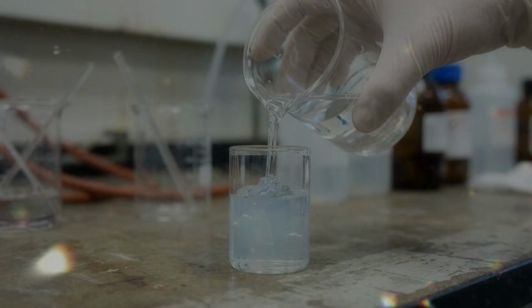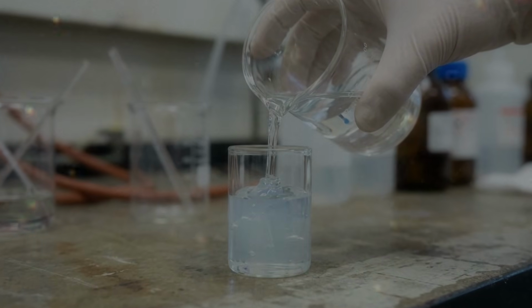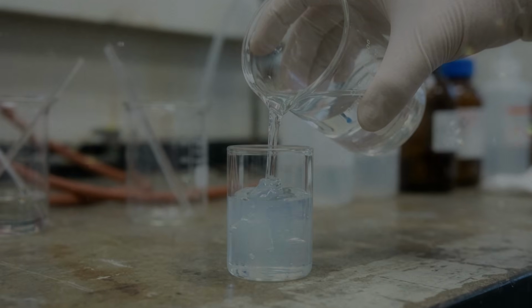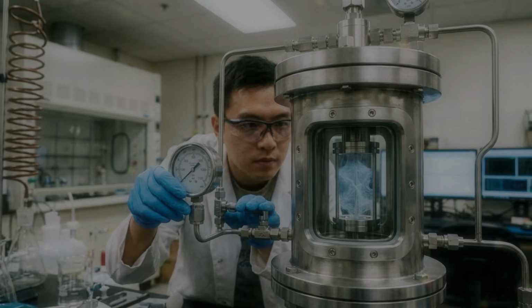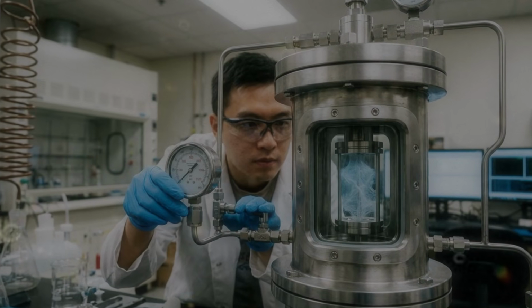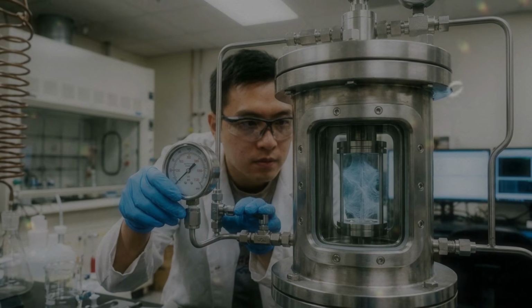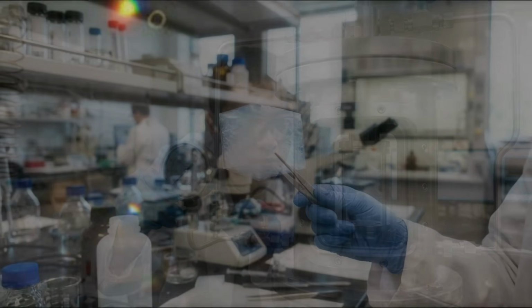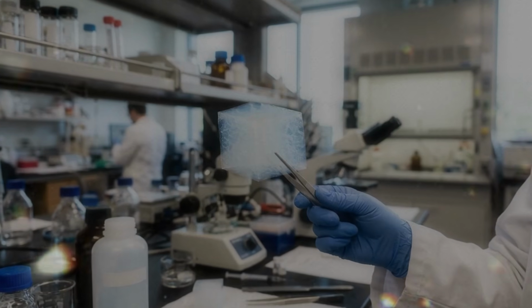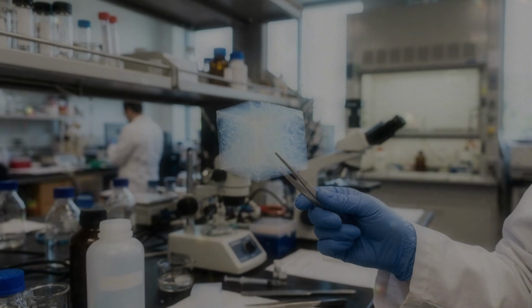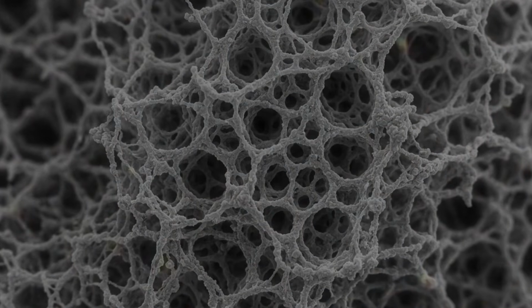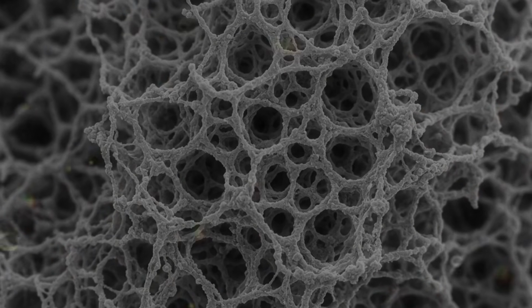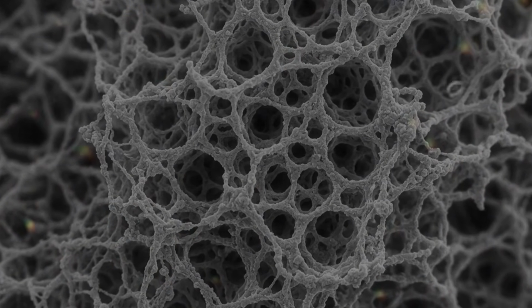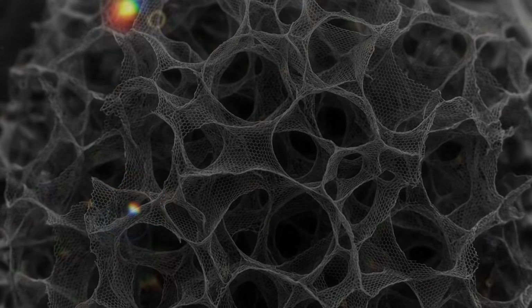A very light electrode may occupy too much volume. Thick electrodes may develop slow regions that charged particles cannot reach quickly. The aerogel must be attached to current collectors, filled with electrolyte, sealed and produced consistently. Graphene sheets also tend to stack together, reducing the accessible surface. Three-dimensional networks help keep them apart, but the network must be compressed enough to fit inside a practical device. Too much compression closes the pores, too little wastes space.